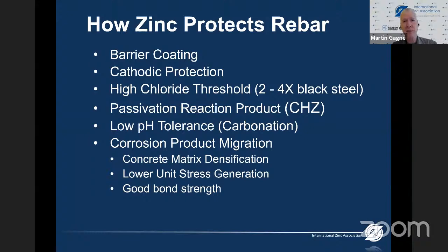So we can see that zinc protects rebar in a number of ways. It's a barrier coating, provides cathodic protection. There's a very high chloride threshold. We see the formation of the passive calcium hydroxyzincate.